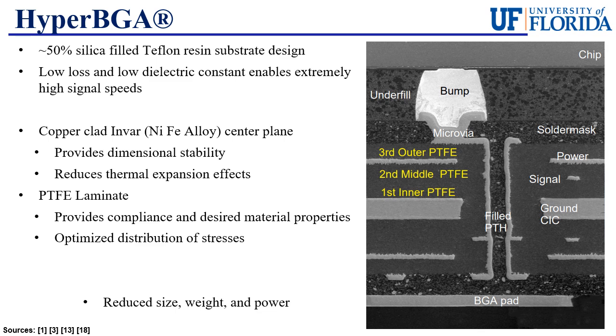And to combat the mechanical instability, a ground plane of copper-clad invar, or a layer of copper surrounded by a nickel-iron alloy, is placed at the center of the substrate. The copper-clad invar center plane provides extra dimensional and mechanical stability, and its low coefficient of thermal expansion helps reduce the overall thermal expansion of the package. And the Teflon laminate that surrounds the center plane provides those desired material properties for the substrate matrix and a little extra compliance to distribute stresses throughout the package. Overall, the Hyper-BGA is a commercial design for an organic packaging substrate that uses clever material combinations to reduce size, weight, and consumed power.